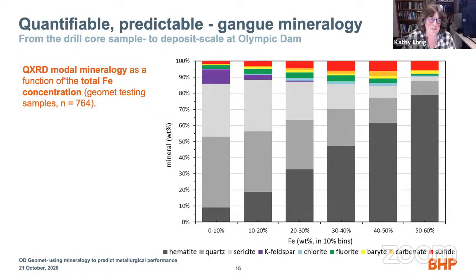So by doing quantitative modal mineralogy and then binning that information based on the iron content, we can look at the percent of hematite. We go up the list: hematite, quartz, sericite, K feldspar, the little blue lines are chlorite, and the green is fluorite. And as we increase in the iron content going across the horizontal axis, obviously the hematite content goes up, the quartz is decreasing, the sericite is decreasing, and the other minerals are doing it too, not the sulfide so much.